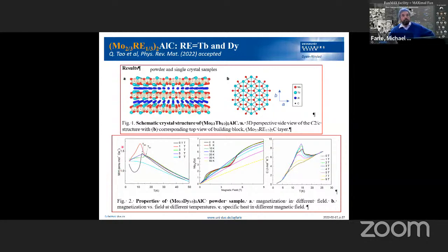Now, when we do a susceptibility measurement as a function of temperature, the fun happens, unfortunately, only below 30 Kelvin. And you see strong dependencies on an applied magnetic field. So let's just keep it at that. This looks like phase transitions when you see a cusp in the susceptibility. This reminds the community of magnetic phase transitions. And it seems at 9 Tesla, this transition is mostly suppressed.